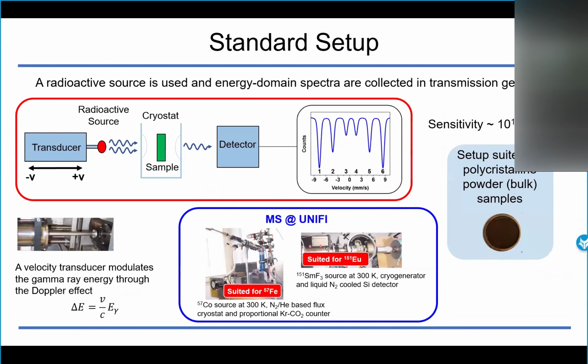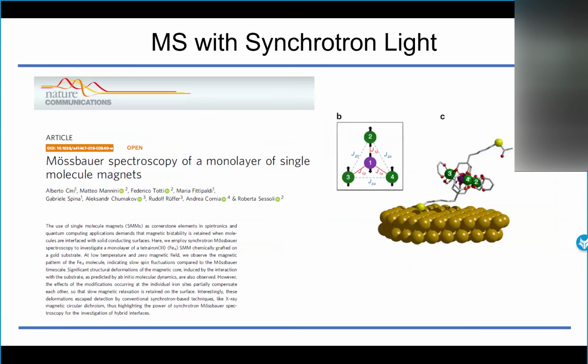In a standard setup, like the one that we have in Florence, the radioactive source is mounted on a transducer that goes back and forth in order to modulate the energy of the gamma rays by means of the Doppler effect. Then the gamma rays interact with the sample, and the transmitted gamma rays are revealed. The sensitivity of a standard setup is suited to study bulk samples. So, in other words, principally to study powder samples. If you want to study thin or ultra-thin samples, then you have to consider synchrotron light, as was the case of a monolayer of single molecule magnets sublimated on a gold substrate.